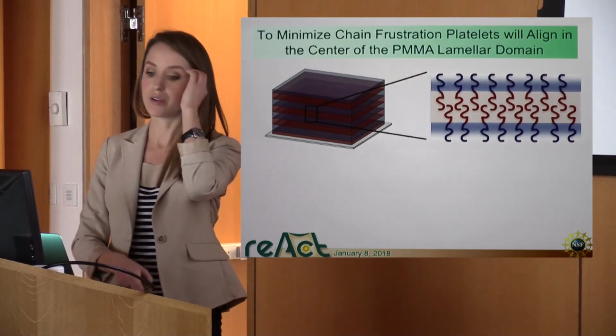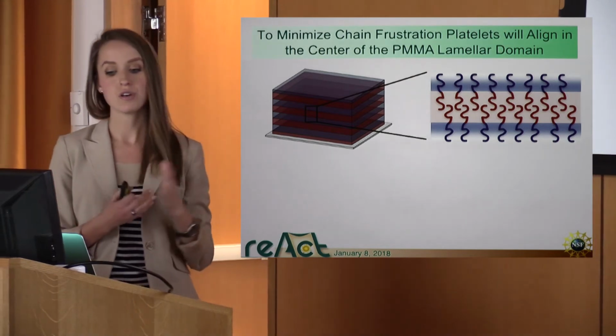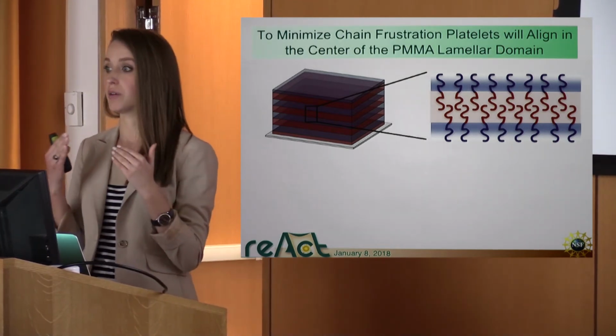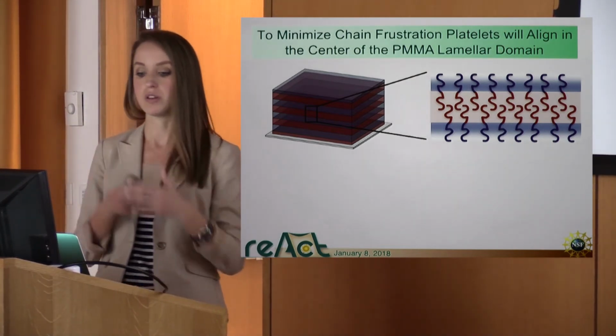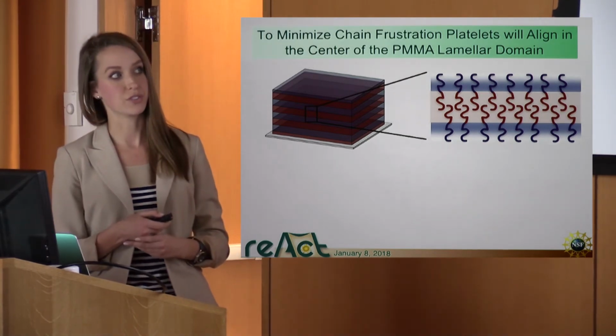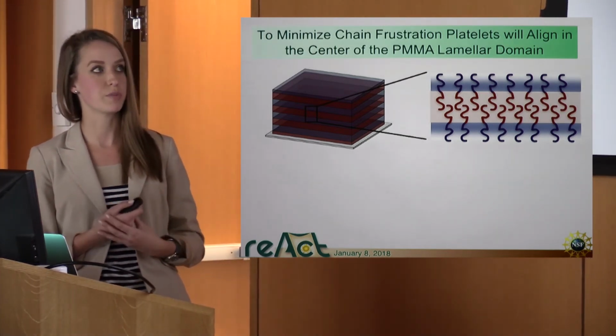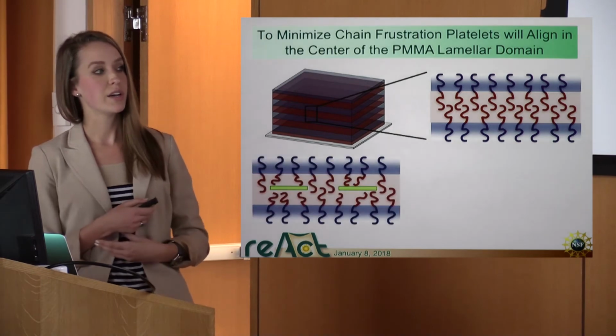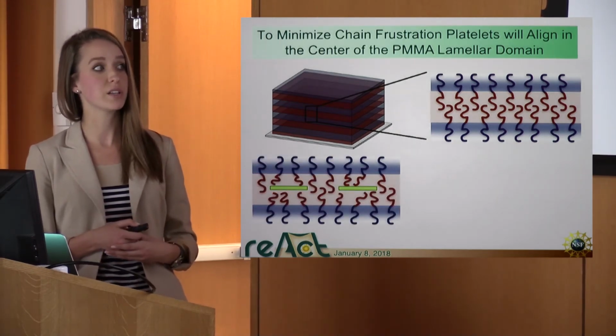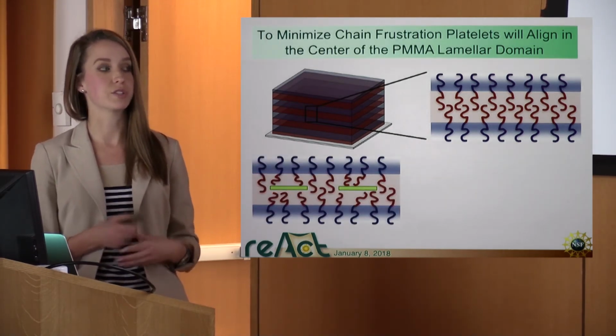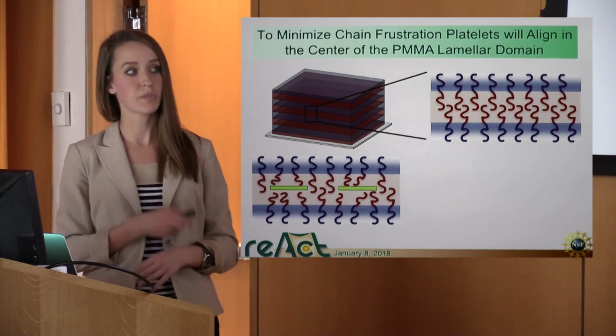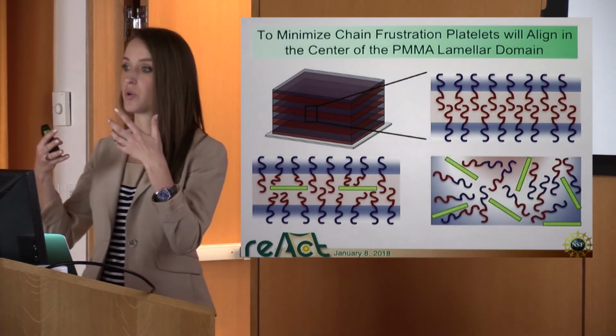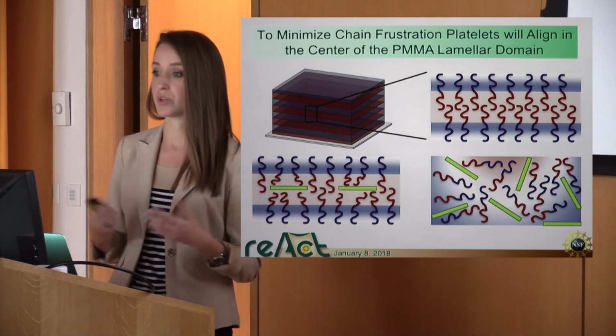Our hypothesis is that in order to minimize the chain frustration, the platelets will align with their smallest dimensions between the block copolymer. So we can, just as a schematic, kind of a 2D representation of block copolymer. As we incorporate these platelets, the local chain conformation around these particles starts to be disrupted. And then once you add too many of essentially these walls between these chains,